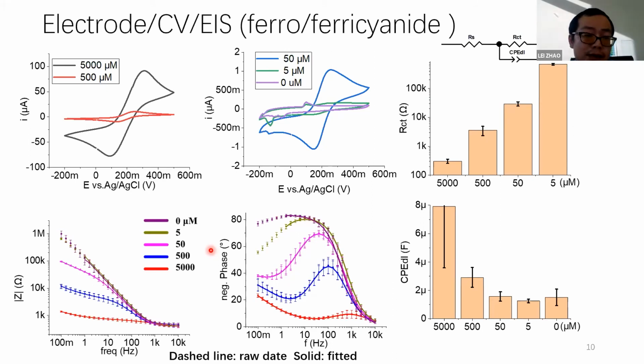Then we checked the electrodes with electrochemical methods. From the CV curve, you can see that with the presence of ferrocyanide, it shows typical redox peaks. Then the electrode can even respond to a super low concentration of the redox probe, which is 5 micromolar. And the change was also confirmed by impedance measurements.